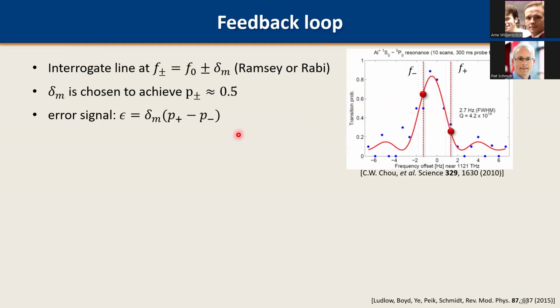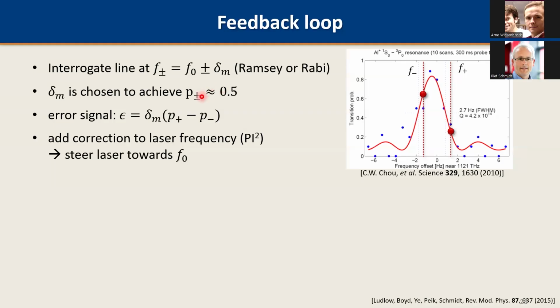Then we can derive an error signal. That's the difference in excitation probability that we measure on this point and on this point, multiplied by the step that we have actually taken. And we can then add this correction to the laser frequency by using an acousto-optical modulator. For example, we tune the frequency of an acousto-optical modulator and then steer the laser's frequency back towards the transition frequency here. We do that typically with a proportional, integral and double integrator system. And I think it's one of the problems that I've written down for you to find out why we need a double integrator. Doing this type of feedback loop repeatedly, we steer the laser's frequency onto the atomic resonance frequency.